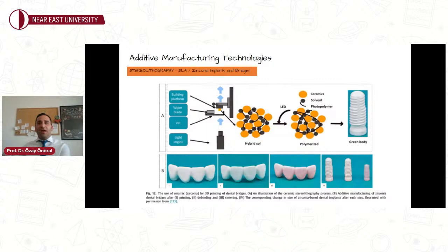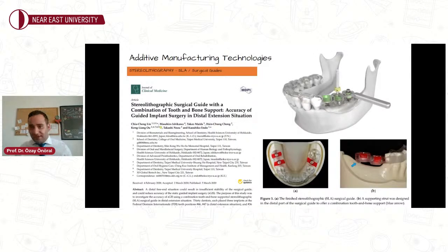The titanium implant has an opaque appearance, and if there is a very thin biotype in your patient, this may reflect underneath, causing an aesthetic issue. And you can fabricate zirconia implants with SLA technology. That's brilliant. It accommodates flexibility in design, geometric shapes, and scaling, resulting in highly accurate personalized devices. For instance, the use of SLA printed drilling templates to transfer virtual implant planning into reality has become a standard fabrication method with navigated implantology, and is superior to other procedures like milling, for example.